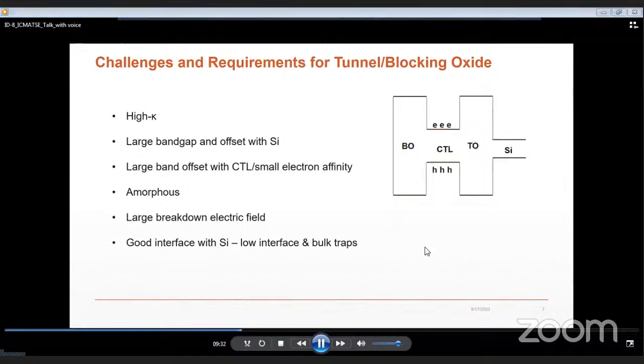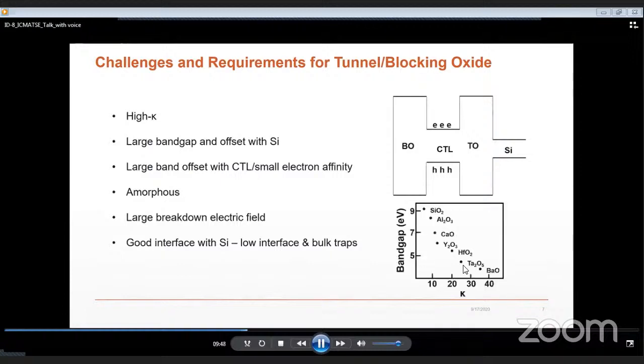The tunnel oxide has to have a large band gap and good band offset with the silicon channel and charge trapping layer in order to avoid charge leakage and thus improve the retention characteristic of the memory. So this means that they must have a small electron affinity. However, there is usually a trade-off: as the dielectric constant of the material is increased, the band gap is reduced.